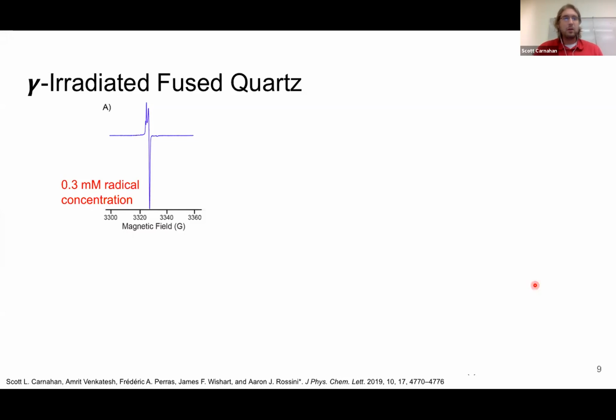I'm going to walk through a bit of our actual data now. After gamma radiation, we had a 0.3 millimolar radical concentration. In comparison, if I'm doing standard cross-effect DNP with TEKPol in TCE, when I make the solution, it's typically a 16 millimolar radical solution. So we get significantly fewer radicals in our sample than when you do the solution.